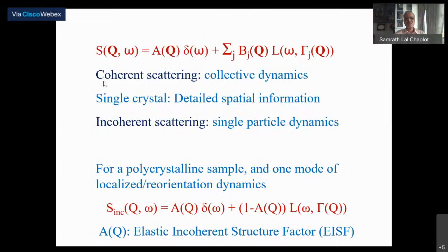So now again, there are issues of coherent and incoherent scattering. Okay, so that's the structure factor we wrote in the previous projection. As we said, this could involve coherent scattering. So far, we have not said anything about whether scattering is coherent or incoherent, because that doesn't depend on the nature of the dynamics; it's determined by the nature of the atoms involved in the dynamics. So, like hydrogen, you will largely see incoherent scattering, whereas if you have deuterium or oxygen or sodium or lithium, you will see coherent scattering and perhaps also a little bit of incoherent scattering. Okay, so that's one part.